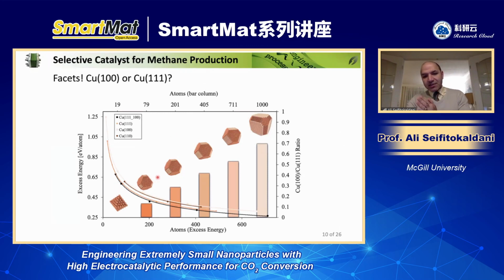Here you just see selected particle shapes at different sizes. But for each size, we had multiple, sometimes a couple of tens of different configurations and shapes, depending on the surface energy and also the facet that we included. So we included the 111 facet, 100 facet, 110 facet, and also 211, which is not represented here because it wasn't stable. And after that, at each particle size, we evaluated the excess energy to see which particle shape at that size is the most stable.